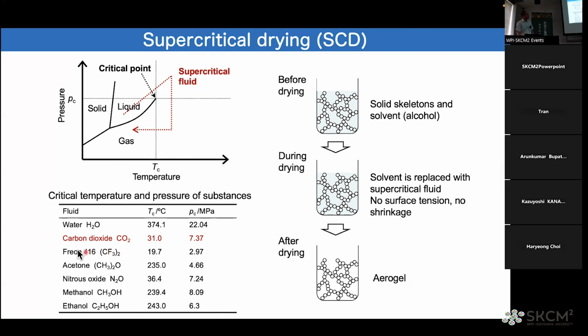And we often use carbon dioxide for the supercritical fluid because carbon dioxide has rather low critical temperature and pressure. But still the critical pressure is rather high, more than 7 megapascals, so more than 70 atmospheres. So I believe it should be avoided. In the supercritical drying process, the drying goes like this. First, the gel contains a liquid, then supercritical state, no shrinkage, no cracking, and after decreasing the pressure, the gas in the pore, so the drying is finished.